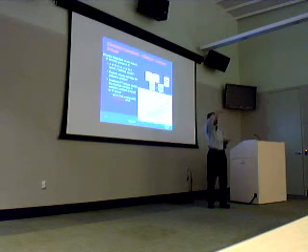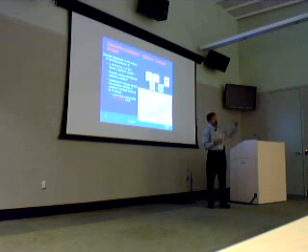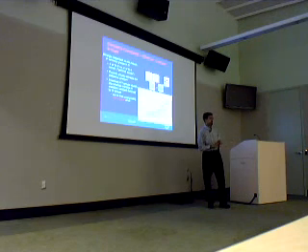And we even did something more complicated. This chip is packaged into a bigger package. So we put in materials which, like pillars, held the stress upwards of this material. So the integration, a material problem, was solved by an integration solution. You essentially make the rest of the structure much harder, and that would absorb the stress so that this material itself will see lower stress. That's the way.